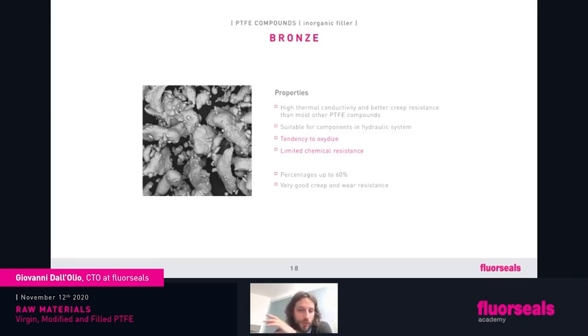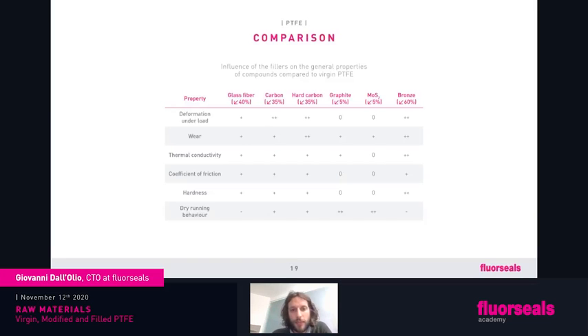Okay, we have seen the most common fillers inside the PTFE. We also have seen that there are some links between the properties that adding a filler to the PTFE will lead to, and we have this table that is showing us what I mean. So we have the different fillers on the top and the properties that we have seen that usually are improved by a filler. We can see that almost any filler had a plus on these properties, mainly deformation under load, the thermal conductivity, the friction that is improved. Remember, it's not always the best thing, hardness, and the dry running behavior.